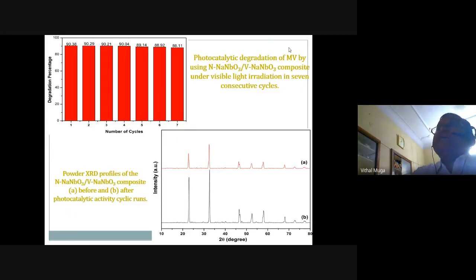Then we have studied whether this catalyst is useful once you use and throw. No, you can actually use it 7 times. My student has used it 7 times against the degradation of methyl violet. Now you see in the first cycle 90.38% decomposed in 180 minutes. In the 7th cycle, 88%. Now why is there a small decrease?